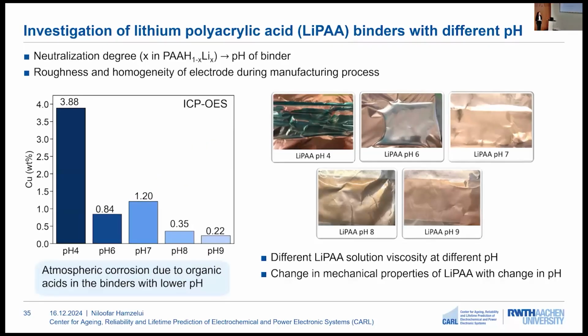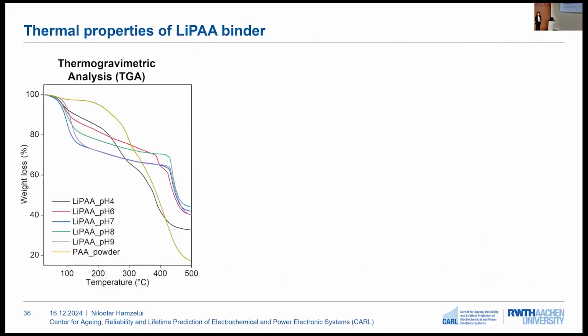The binders were detached from the copper current collector, and ICP measurements were performed on the binders. It was observed that at lower pH, we see a higher copper content in the binder, which is the reason why the color of the binder changes to blue-green, and this effect is less for the higher pHs of the binder. This can be due to the atmospheric corrosion of the copper current collector in connection with the acids within the binders, which have a lower pH.